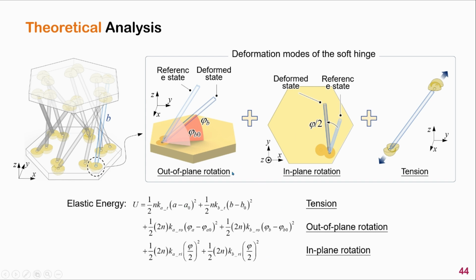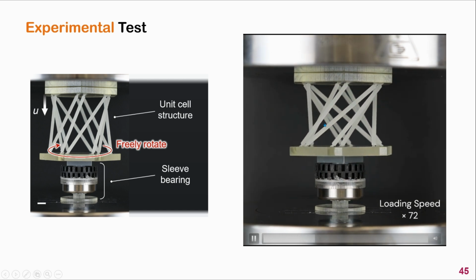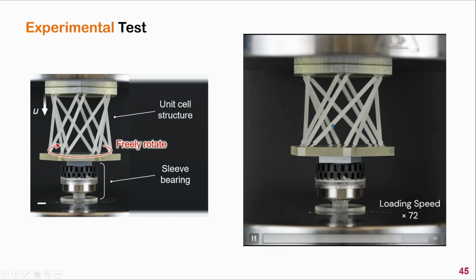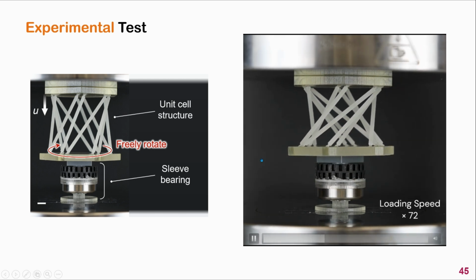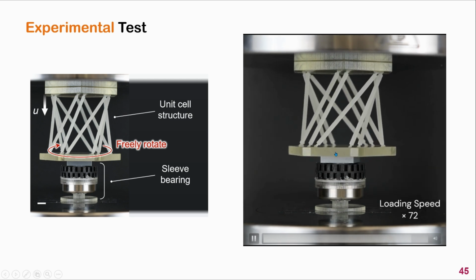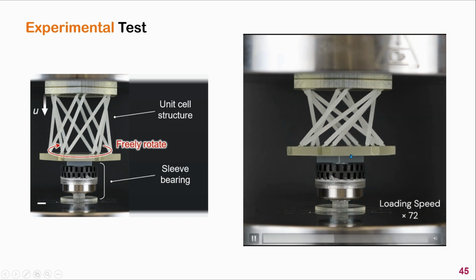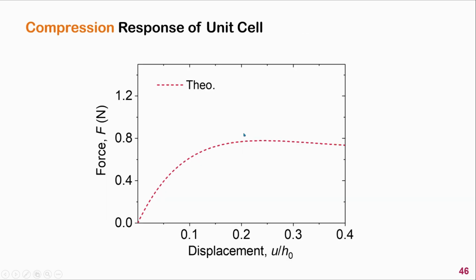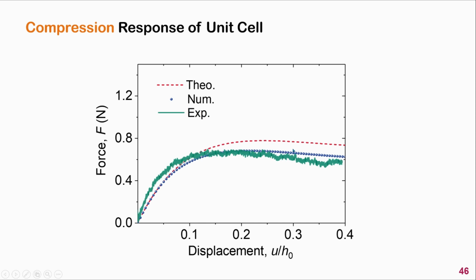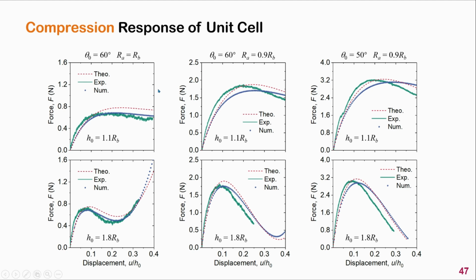To examine the analytical model, we fabricated the unit cell structure using multi-material 3D printing and performed the comparison test. In the experiment, the bottom plate is mounted on a sleeve bearing that enables the plate to rotate freely during compression. This is the force displacement curve given by the analytic model, and this is the finite element simulation result. This is the experimental measurement. We can see that our very simple analytic model can effectively predict the response of the unit cell structure. And these are the results for other geometric parameters. In each case, the analytical model works very well.